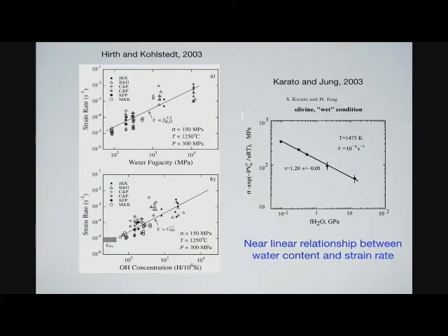Yep. So it has been known, and these are papers from 2003, but the experiments showing that water affects the rheology of olivine go back much earlier, into the 80s. And before that, people started observing, in particular for quartz, that water does weaken rocks considerably in deformation. And this is a compilation from 2003 from Hirth and Kohlstedt, in this case concentration of water versus strain rate. The same thing here, that's really strain rate overall versus concentration of water.